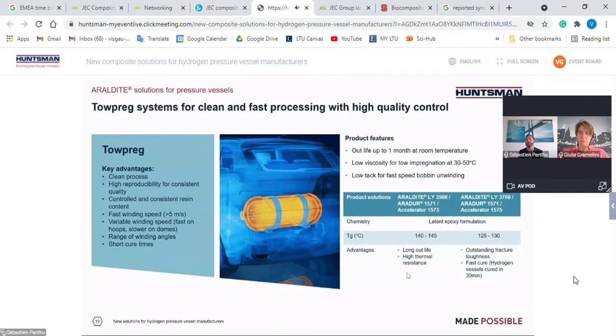And another point is that we work on a low viscosity concept to make a very easy and fast tow impregnation, even at low temperatures like 30 to 50 degrees Celsius. And then the last characteristic is that we work with low tack, because when you unwind, when you are manufacturing the pressure vessel, you need to go fast and you cannot stick. So the bobbin should be able to release the tow easily.